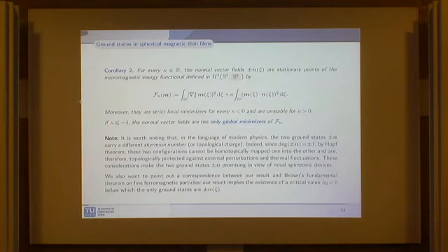So now we are coming back to the micromagnetic setting. We are able to prove that on the sphere there are magnetic skyrmion configurations. These really are plus and minus the normal vector fields. And actually, these two configurations have two different topological degrees, because plus and minus n have topological degree plus and minus 1.